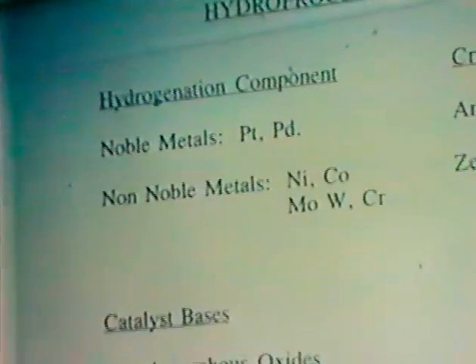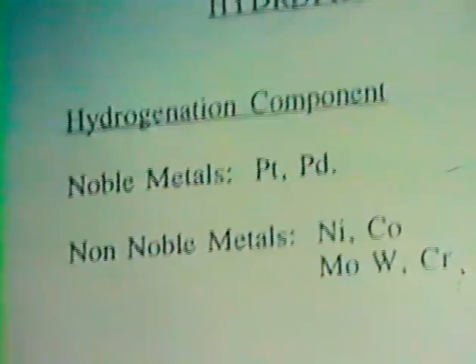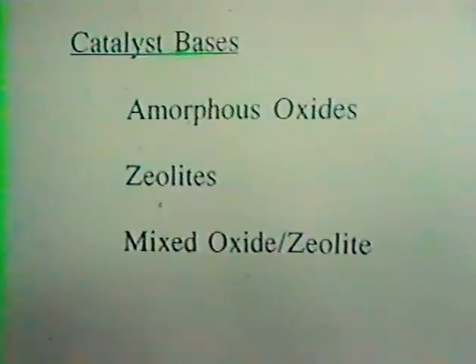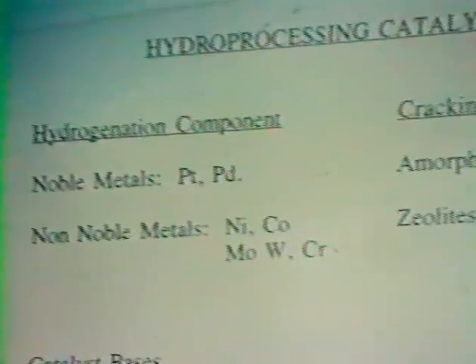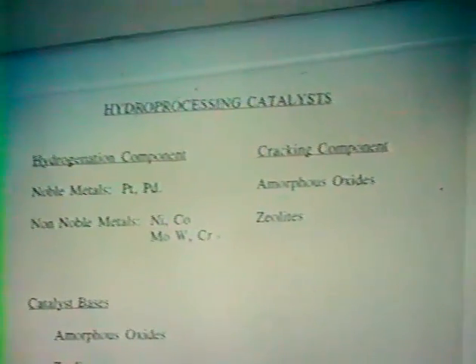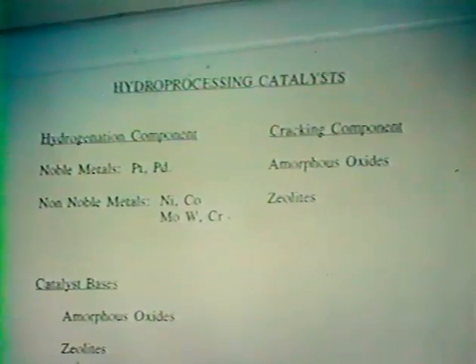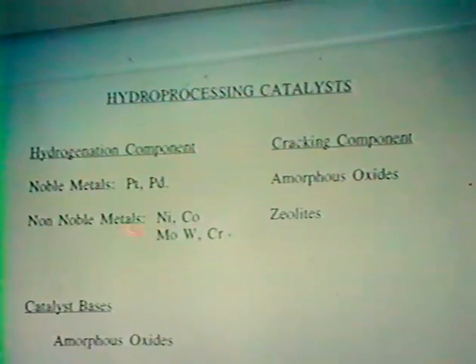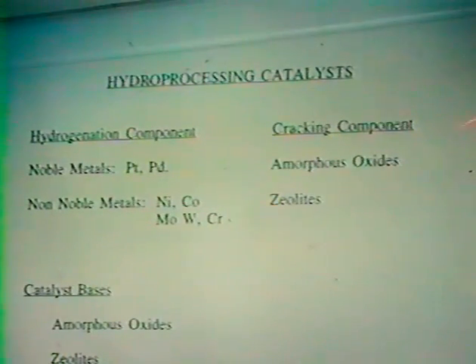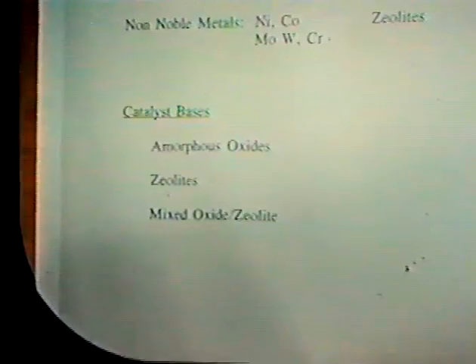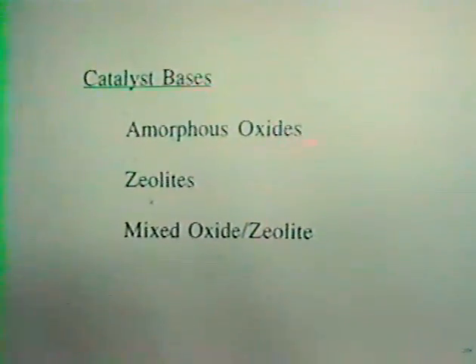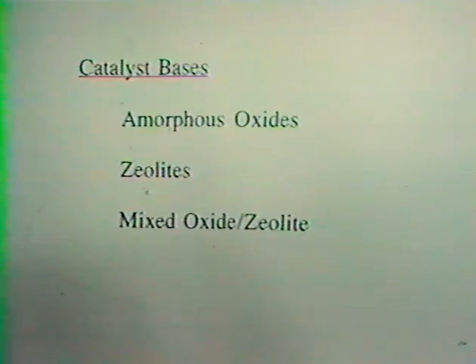What I'd like to do now is to move into the area of hydroprocessing, which is possibly one way where we can engineer and do catalysis to get around some of these problems. I'm particularly talking about hydrocracking catalysts, which many of you know are bifunctional catalysts that consist of a hydrogenation component, noble metal or non-noble metal, mounted on a cracking component support. The catalyst supports can usually be structured into three areas: total amorphous oxides, essentially all zeolite, or a mixture of oxide and zeolite. I'm going to talk mainly about these two areas.